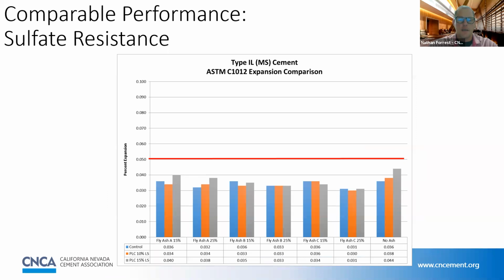We'll also take a look here at sulfate resistance. What we've got, same color scheme as before, ordinary Portland cement in blue, PLCs in orange and in gray. And we have 3 different fly ashes, A, B, and C, tested at both 15 and at 25% replacement values. And we can see that these concretes were resistant to sulfate at all doses. Again, comparable performance to ordinary Portland cement.